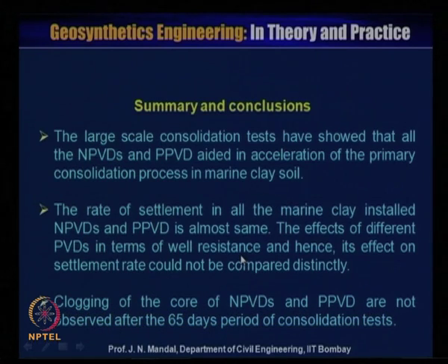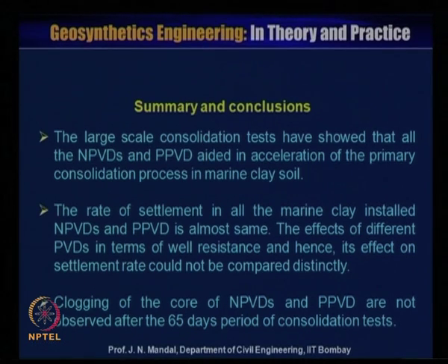So, what is the summary and the conclusion? Large scale consolidation tests have shown that all the non-woven prefabricated vertical drains (NPVDs) and polyester prefabricated vertical drain (PPVD) aided in acceleration of the primary consolidation process in marine clay soil.